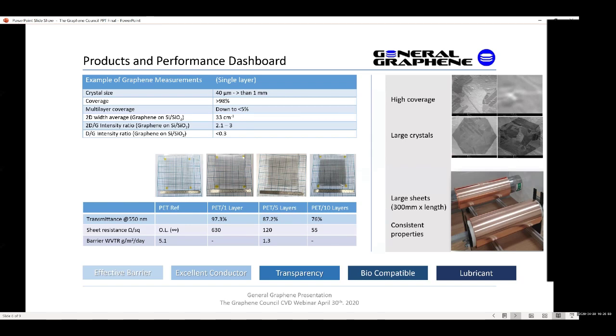So starting with the above table, this dashboard presents us the snapshot of graphene characteristics typically measured in our laboratories. We don't make standard products, so this is showing the range of properties we will typically test. So in the top table, note that we design a wide range of graphene properties tuned to the very specific customer applications. We are able to change crystal size from large to very large crystal sizes. The ones you see there are around 40 micron, and we can produce crystals greater than 1 millimeter in width. We can also alter the surface coverage precisely and precisely determine the number of layers, control the incidence of multi-layers and other defects.